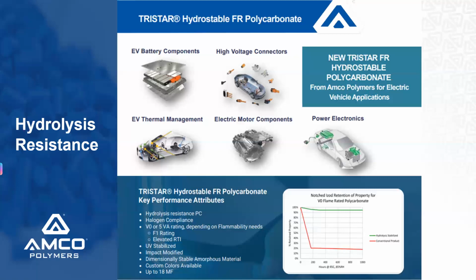Hydrolysis resistance. Roughly a year and a half ago, 2 years ago, we were challenged by one of our major customers to improve the hydrolysis resistance of polycarbonate. They mold a box that is used all around the world, but typically when you get towards the Tropic of Capricorn and Cancer, those areas tend to be high humidity, high temperature, and they were seeing some failures in the material that they were currently using.